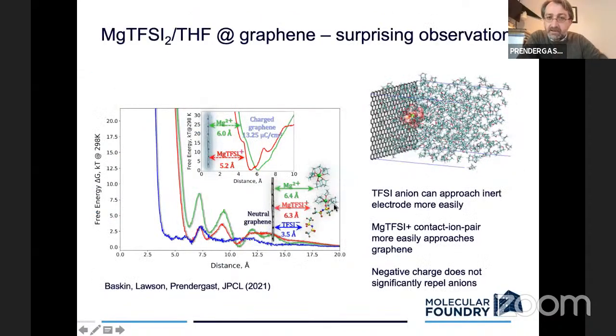Okay, all that was talking about the bulk phase. Now let's get to the interface. So this is an example where if you explore the free energy of different species as a function of distance from an inert electrode, in this case graphene, what we find is that there's some surprises here. The anions in this particular case, again, because it's an organic solvent, it only really can coordinate objects that are positive. The anions are very unhappy in solution. They're really only there because the cations are there. And so if they can approach an interface, they will, and tend to populate the interface in excess.